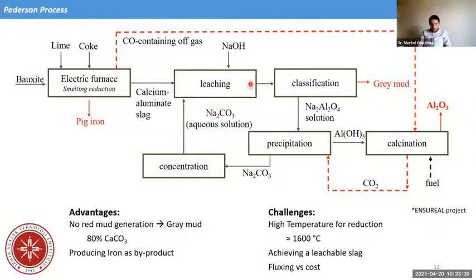And in the leaching, in hydrometallurgy, the phases must be leachable. And this leachability changes a lot with the primary ore source. What you add in the electric furnace changes the composition and phases in the slag, and this directly changes the leachability. And it is not very easy to control the ore concentration, and this can be an issue and challenge in that way. And another challenge is the fluxing. You cannot easily reduce the bauxite just as it is, because then you need higher temperatures. To lower the temperature, we use an additive, which is lime, and lime is not very cheap, so it increases the cost too.